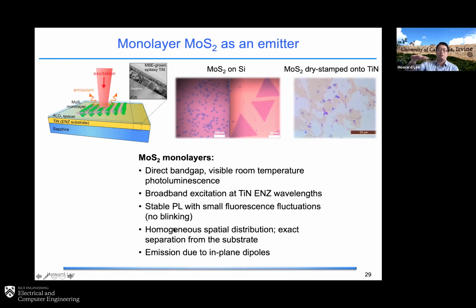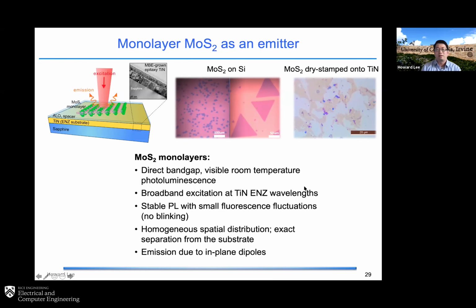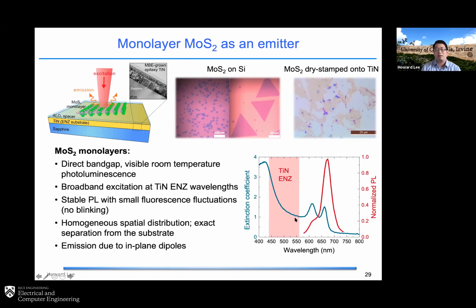Also, they're quite homogeneous, meaning you have just a monolayer. You can really control the spacing between the emitter and the ENZ material quite exactly because they are a monolayer on the surface. And they have an in-plane emission, so you can model that quite easily. If you look at the absorption coefficient, you can excite this MoS2 in the visible range, and then it emits photoluminescence around 680 nanometer, the red curve here.